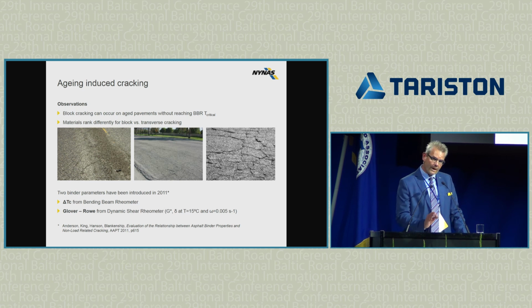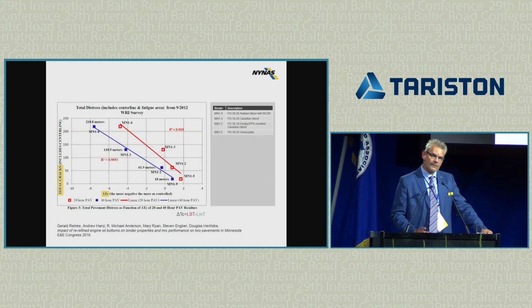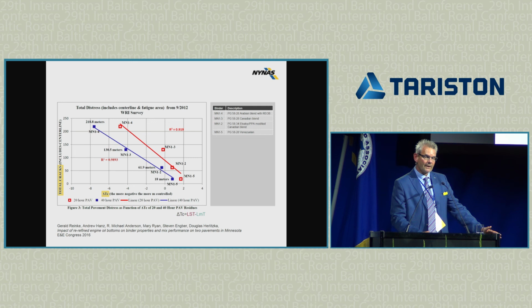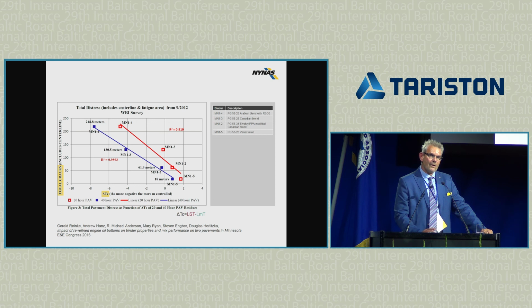Now, why is this important? It's quite important because last year, Gerald Reinke and his colleagues published a paper at the Eurobitume conference, and they showed field performance. Basically, they looked at cracking of field sections, and they compared that to the delta TC of the binder recovered in the pavement. And you could see that delta TC was an important driver for the cracking of these field sections. So it's quite important to see that there's a link between the performance of the asphalt and this particular parameter when it comes to bitumen.